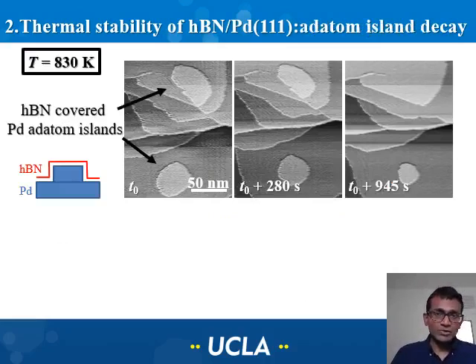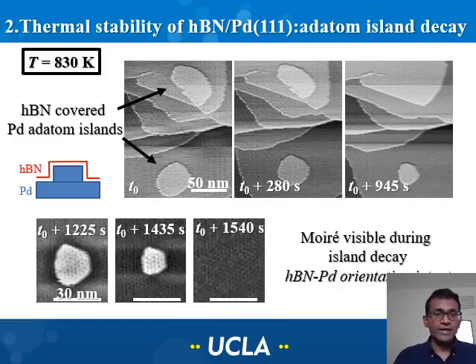Now, compared to a hexagonal boron nitride covered palladium, if you take bare palladium and anneal it in vacuum, this is what we observe. So these are adatom islands on a palladium surface, and it's clean, no boron nitride on the surface. As time progresses, these adatom islands disappear as part of the ripening process. They lose their atoms to the step edges or to larger adatom islands in the vicinity. And this is a higher magnification image obtained from hexagonal boron nitride covered islands, and we observe these adatom islands go away, and this is a higher magnification image showing that the moire pattern remains and these adatom islands disappear under the moire.